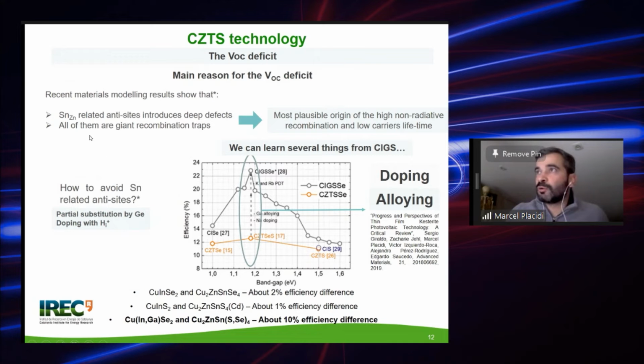Very recently, in fact a couple of years ago, in this paper, Aaron Walsh's group demonstrated that it seems the VOC deficit will come from tin-on-zinc anti-site deep defects, which are created with these structural defects. And these create giant recombination traps. This could explain the low VOC observed to date in all the kesterite devices fabricated.